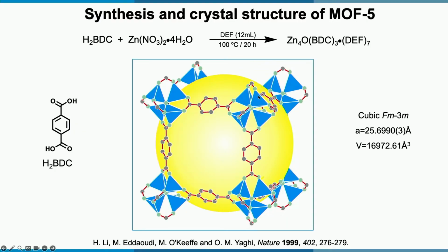This crystal is a primitive cubic made from tetrazinc units. Again, the dicopper acetate that I described, and the molecular version of this tetrazinc cluster called basic zinc acetate, have been known since Bragg's time in the 1930s, where he was studying them with X-ray crystallography. So they've been known for a long time in chemistry, but no one has either thought about linking them together or succeeded because of the crystallinity challenge.